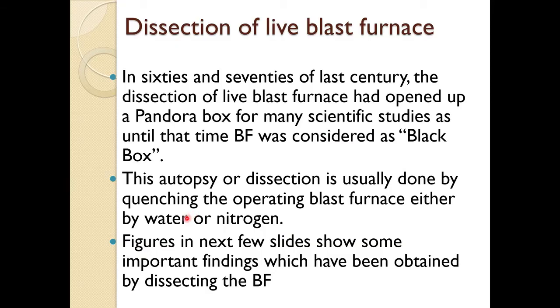Researchers, especially in Japan and the USA, quenched operating blast furnaces using water or nitrogen from the top and then dissected them. In Japan, almost 10 to 12 blast furnaces were quenched in one campaign. This study, conducted about 3 to 4 decades ago, provided remarkable findings about the internal structure of the blast furnace, and has since led to major improvements in modern blast furnace design and operation.